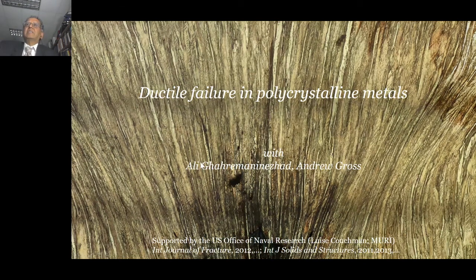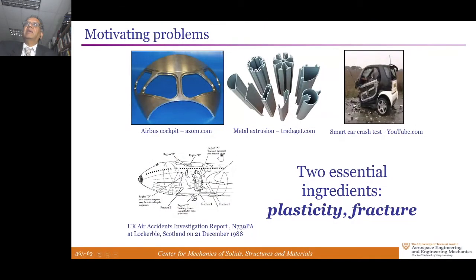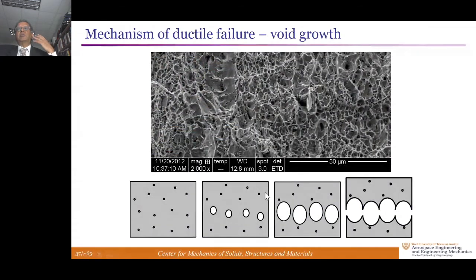The second one is similar materials, polycrystalline materials, but now ductile failure at slow strain rates, commonly encountered in a number of applications of forming and things like that. There are two essential ingredients in making predictive models for these applications, plasticity and fracture. It turns out fracture is just the endpoint of where plastic deformation leads to localization. And you need to have very careful experiments to identify strain levels at which these things happen. Ductile failure immediately brings up this idea that there is void growth and coalescence processes going on. And if you look at fracture surfaces, they do indicate that you have dimples on the surface, which are evidence of cavities that have formed and coalesced.